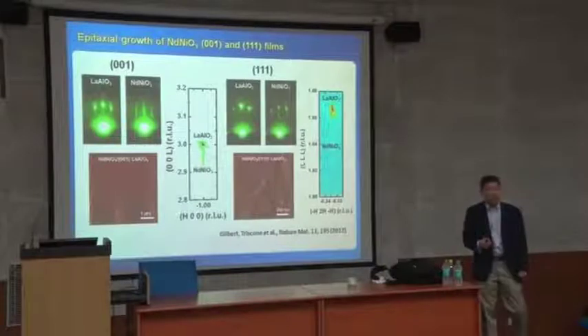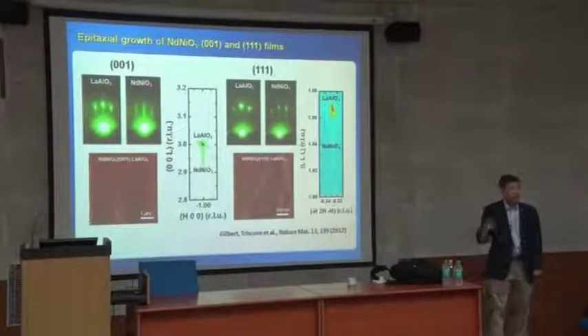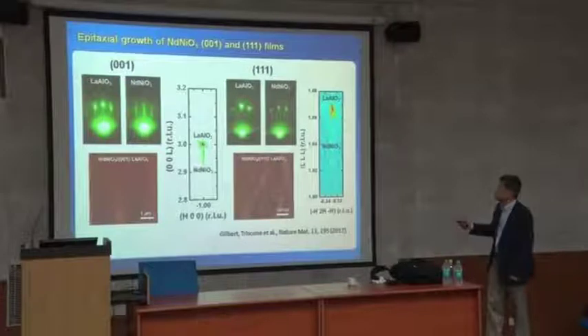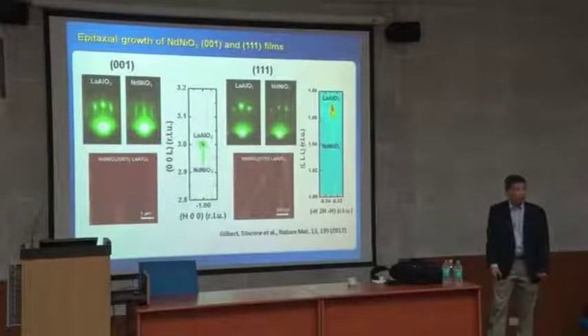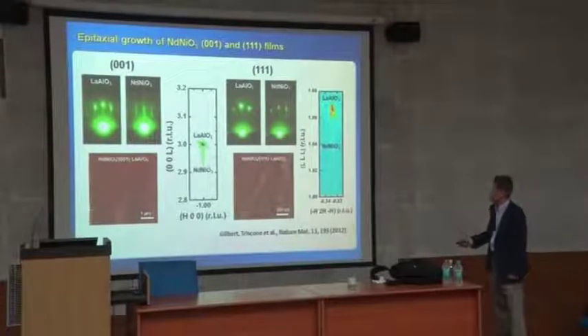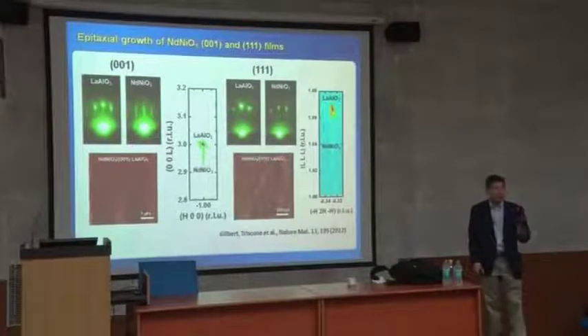But you want to make sure 111 grows very well, and that's something very, very challenging. I'll talk about the 111 growth later. But in here, 111 growth is done using low temperature growth. And then 100 and 111 are very similar types of thin film surfaces. So that means at least we can grow atomic layer controlled, extremely smooth, high quality thin films, both 100 and